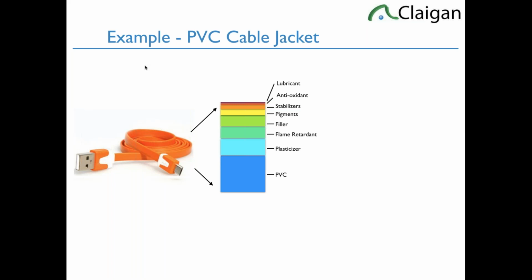Stabilizers. PVC is not naturally thermally stable. At different temperatures, the durometer, i.e. softness or flexibility, will change. It'll also potentially degrade with different temperatures. So it has stabilizers in it to prevent a significant change in physical properties with temperature. Also, if the cable has to go outside and it's exposed to UV light, it often needs UV stabilizers to stop sun fade or degradation in the sun. So PVC normally has stabilizers, at a minimum thermal stabilizers.